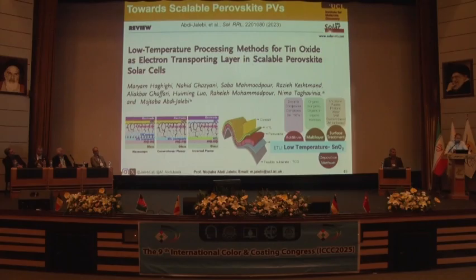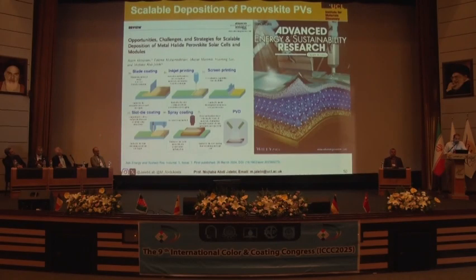So in the past couple of years, we developed materials based on tin oxide that can be prepared at low temperature. And in this work, we explain thoroughly what processing techniques to use. The other thing which is relevant to this community here is the range of coating techniques you can use for perovskite solar cells. You can see that this technology is very versatile.